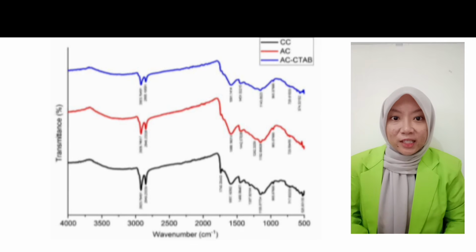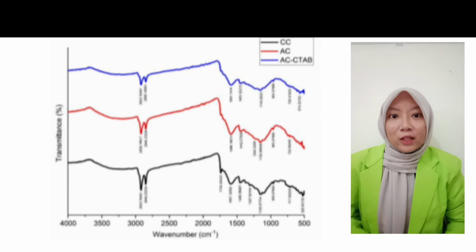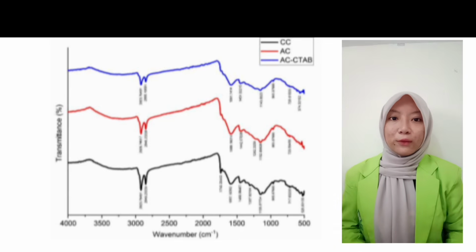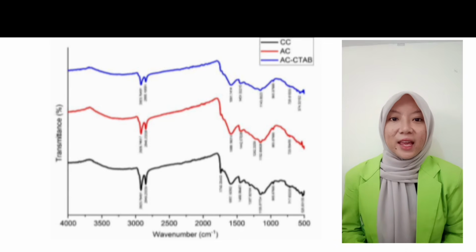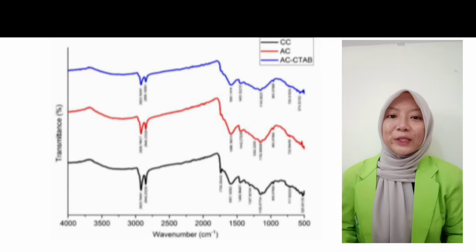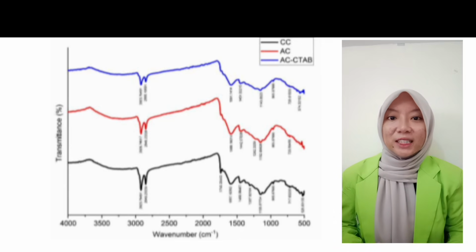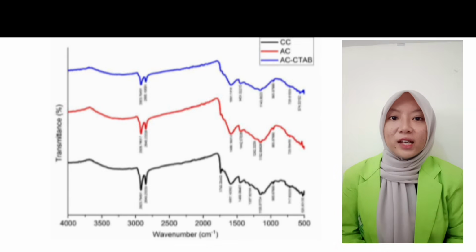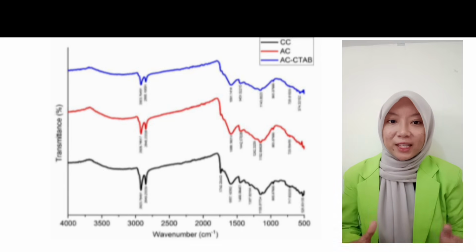Following sulfuric acid activation, the absorption band at approximately 1740 wave number, assigned to the C=O stretching vibration, disappears. In addition, shifts were observed from 1597 to 1588 wave numbers, corresponding to aromatic C=C, from 1457 to 1442 wave numbers, corresponding to aliphatic CH or aromatic ring, and from 1156 to 1153 wave numbers, corresponding to C-O stretching vibration respectively. These changes indicated sulfuric acid activation altered the surface functional groups through dehydration and structural rearrangement of the carbon matrix.